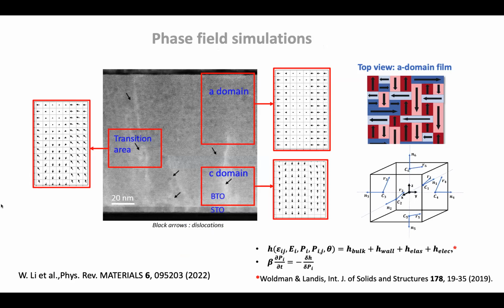There's a cube and there's polarization, dielectric tensor, everything is stored there on a mesoscopic scale. And so it allows you to model something like this, and you can see what polarization is doing, what your dielectric tensor is doing. It shows me that under these strain conditions, at the bottom, I'll have C-oriented domains, and then there's a transition region.